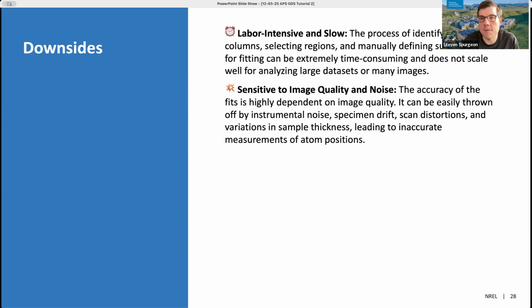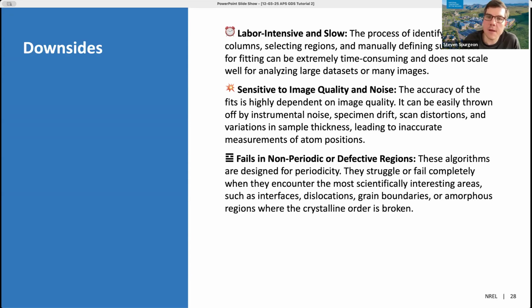And so I already talked about the effect of artifacts in imaging, but many of our experiments are conducted in low signal to noise scenarios, and these models tend to perform very poorly in those scenarios. Third thing is that these models tend to fail in non-periodic or defective regions. And so this is really important that they require a periodicity in the lattice. And if that periodicity doesn't exist for whatever reason, the fitting process can fail. We can get stuck in these kind of local minima that aren't necessarily representative of actual atomic positions. And so as a material scientist, I'm very concerned not just with perfect lattices, but dislocations, grain boundaries, amorphous regions where order is broken, and these models tend to fail in those areas.